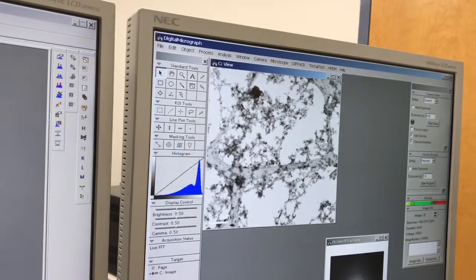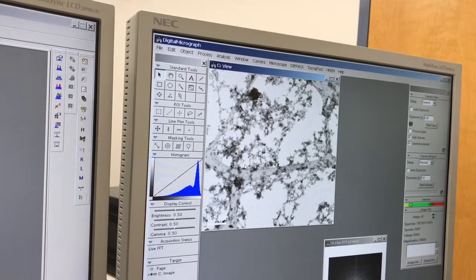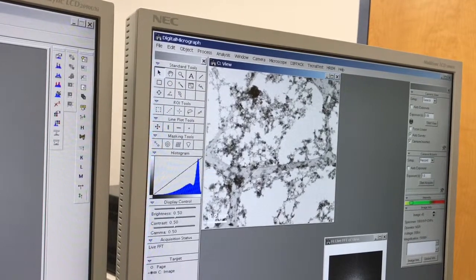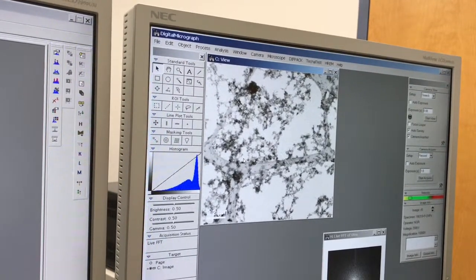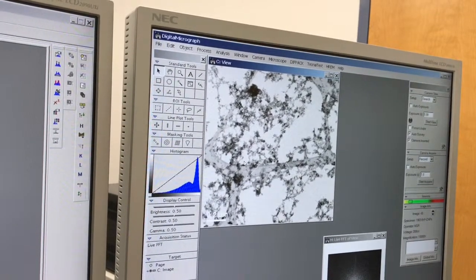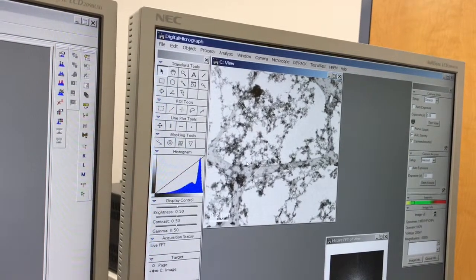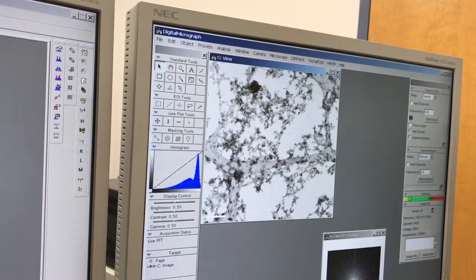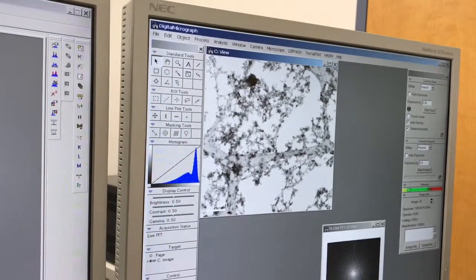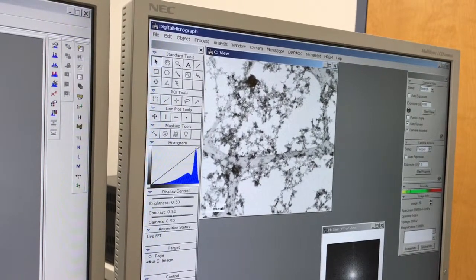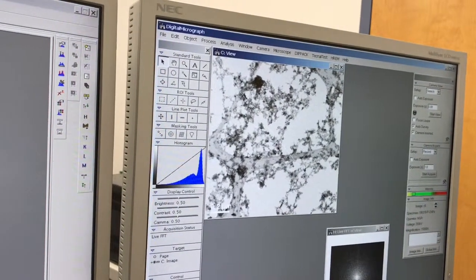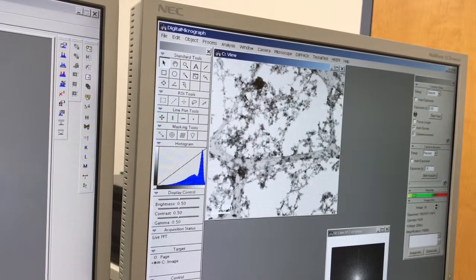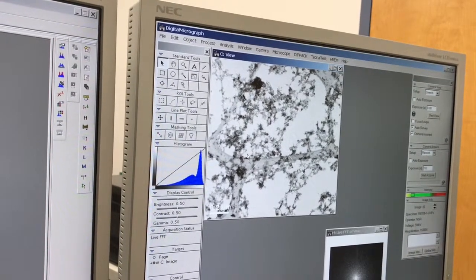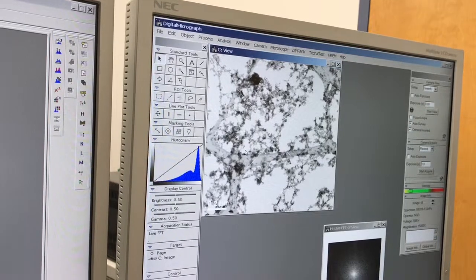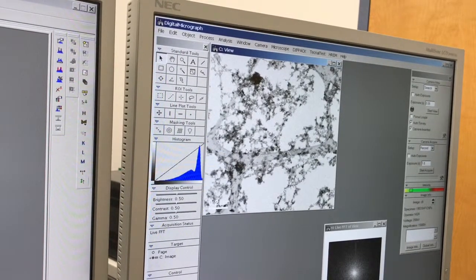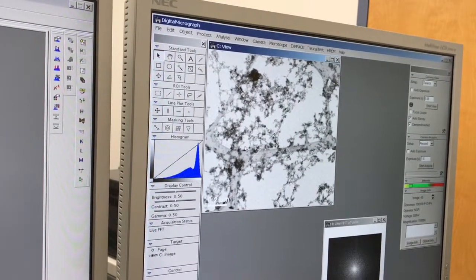Now when you're live imaging, I usually don't go above 0.1. That's a personal preference. I usually don't find that it's necessary to go higher than that. Again, when we're talking about just general bright field and or high resolution imaging, under certain conditions you may have to go longer than that. But for just general bright field high res, I find that that's usually sufficient, again under the assumption we're operating at spot size 1.